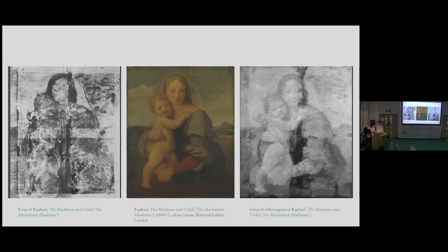Here we can see one of many case studies of such treatment. This one is from the National Gallery. It's the Madonna and Child by Raphael from around 1509 till 1511. According to Jill Dunkerton's study of the painting, in the second half of the 18th century, this painting underwent a transfer from panel to canvas, a procedure that originated in Italy and gained popularity in 18th century France. This method was believed to be a safeguard for paintings from deterioration caused by unstable wooden support. The transfer consequences include, in this case, large missing areas of the original paint.